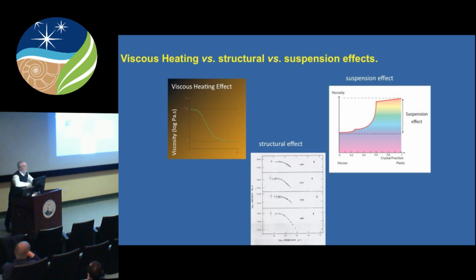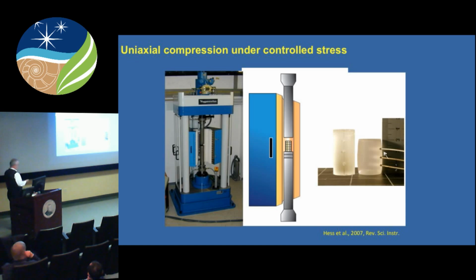So there's three things that we know must be happening as we cross this liquid to solid transition. There must be some viscous heating nearby. There must be the structural effect of the liquid being torn to pieces. And there must be some suspension effect, because we have lots of crystals and bubbles in there which have a physical effect as well on the prediction of the viscosity of the entire bulk of the lava. And so we try to pick these things apart one by one,